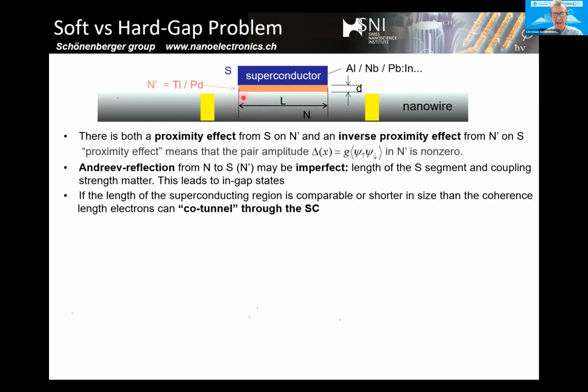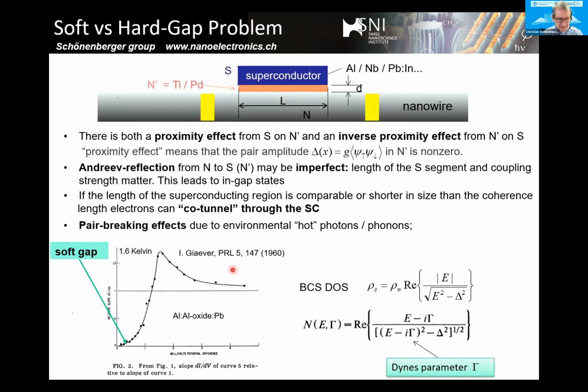There are other factors that can play a role in our experiment. If you evaporate superconductors which are not very long, let's say a contact length of maybe 300 nanometers, you can still tunnel essentially through the superconductor. You can co-tunnel through the superconductor to the normal lead, and then you see a normal density of states, which has nothing to do with a real soft gap problem. But there are other things like pair-breaking effects, finite temperature, and so on. And the interesting thing is that this issue of soft gap started when people were making the first tunnel barriers, and they saw soft gaps, and it's still with us today.